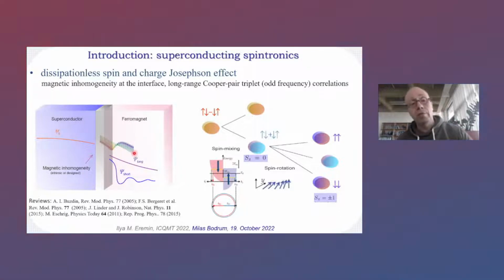The idea comes from the discoveries done by Bergeret, Volkov, and Efetov, and also a number of other groups. There are a number of reviews on this, which I'm citing here. I'm also citing original papers on the next slide. But the idea is the following. You have a superconductor, which is typically a spin singlet superconductor. What is known is that if you have a ferromagnet with an inhomogeneous magnetization at the interface between the ferromagnet and the superconductor, the quantization axis is rotating. Which basically means that when the spin singlet Cooper pair wave function penetrates into the ferromagnet, its quantization axis starts to rotate.